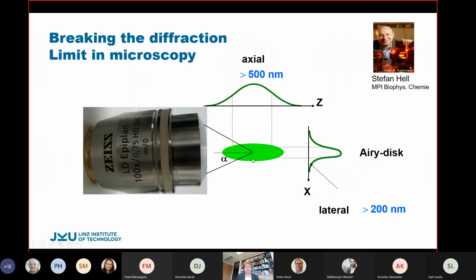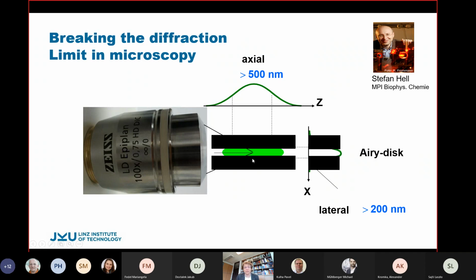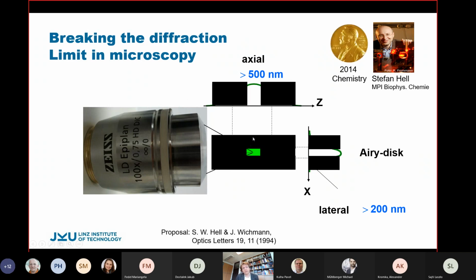That limits your resolution, unless, and that was the cool idea, you can switch off the fluorescence by some means to the left, to the right, or above and below the focal plane. And if you can switch off the fluorescence very, very quickly, so you switch off the fluorophores before they can emit the fluorescing photon, then you are left over with a very small focus, and that should improve your resolution. And for that, he received the Nobel Prize in Chemistry in 2014.